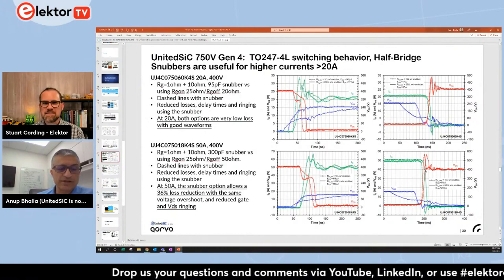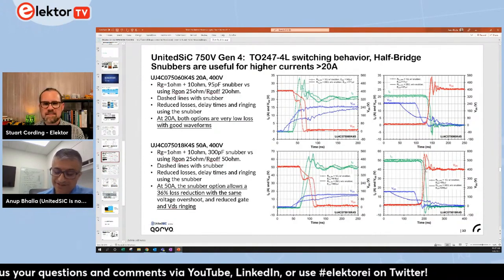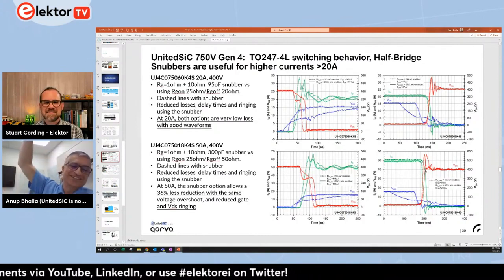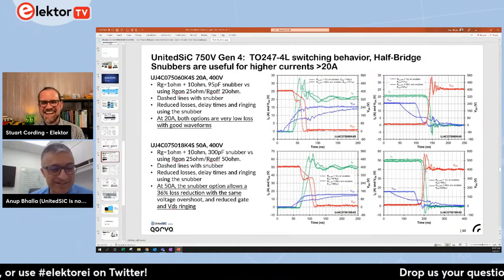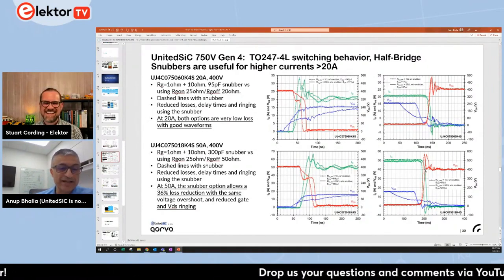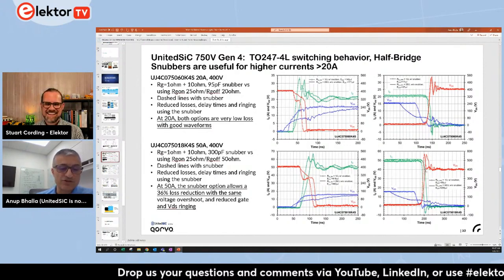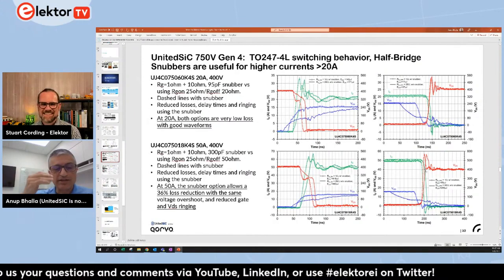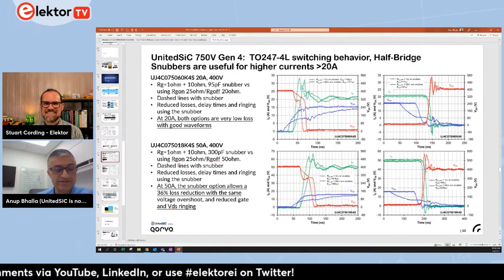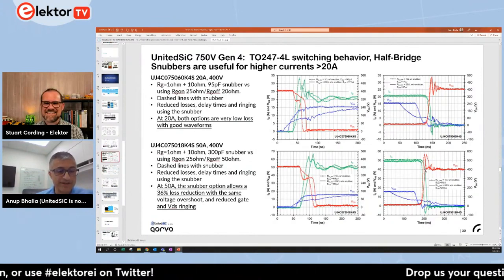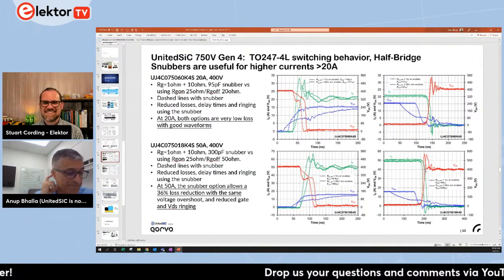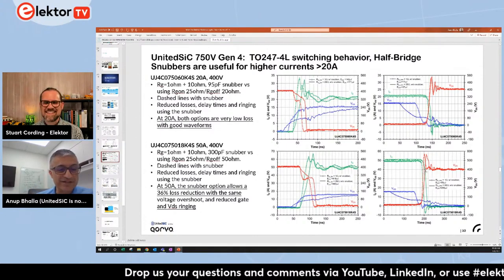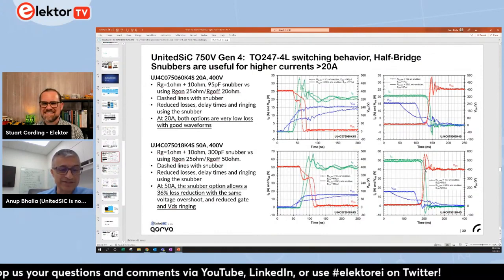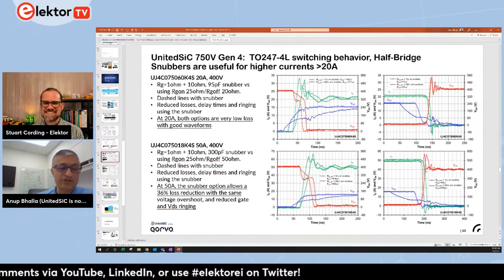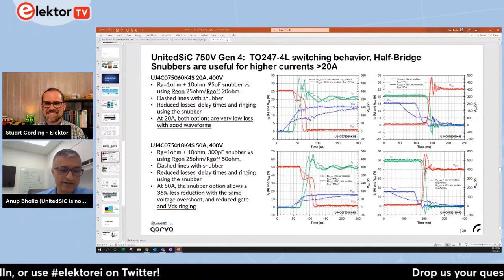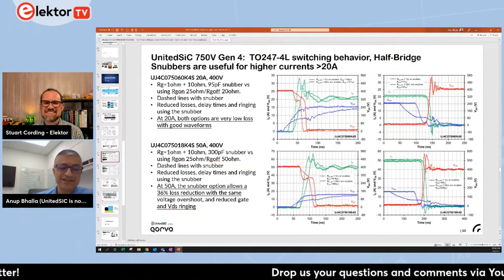You start with a single crystal silicon carbide wafer. It's just that the silicon carbide wafer comes from a boule, which is just this big compared to the silicon one that is enormous. So that affects how much the starting material costs. It's much harder to create. And then it follows the same process. You grow an epitaxial layer on it, which is the layer that supports all the voltage in a vertical current carrying device. Silicon guys, we did that in silicon, we do that in silicon carbide. It's much harder in silicon carbide because instead of at 1000 C, you've got to do it at 1550 or 1600 degrees Celsius. That's above the melting point of silicon. And then it's prone to a lot more defects, and the material is much more imperfect compared to silicon. It's very good now, it's evolved a lot, but it's still not silicon.